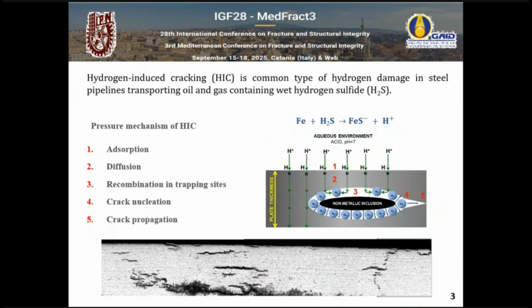Atomic hydrogen doesn't like to be in the atmosphere, so it diffuses very rapidly, in a matter of minutes, into the metal. And once it is in the metal, it keeps diffusing inside until it reaches some suitable trapping site where it recombines back to hydrogen gas, where the fugacity of this reaction is about 1,000 to 3,000 atmospheres. So the pressure is very high, so it cracks the material. And then as the hydrogen accumulates in this cavity, the cracks keep growing, but they grow internally.